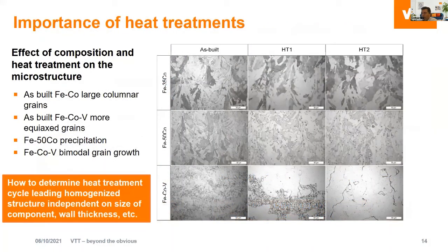And as mentioned, the heat treatment is a really important step also on the additive manufacturing side. And one special feature is that you are typically not able to use the conventional heat treatment routes, even for those standardized materials. That's because after this laser powder bed fusion, the structure is more or less like a welded structure. And the main question is how to normalize that type of structure.